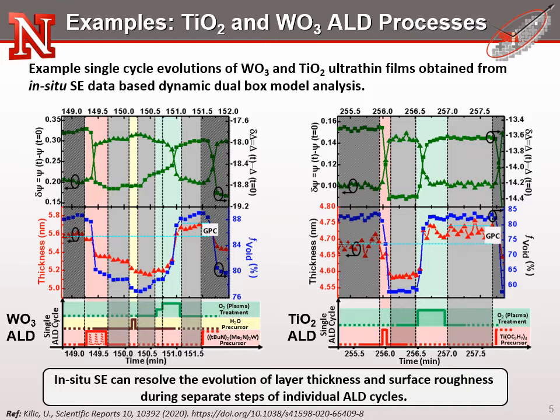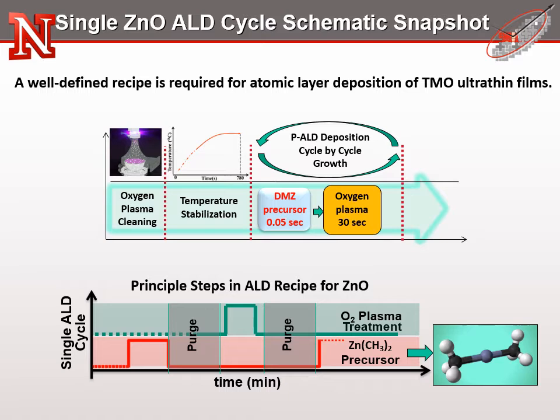As a consequence of cyclic exposure to precursor materials, we observe cyclic surface roughening with fast kinetics and subsequent roughness reduction with slow kinetics. This process leads to the oscillation of the thin-film thickness with small growth per cycle. Here, we would like to use this knowledge and study the in-cycle kinetics of the zinc oxide ALD process. However, first, the ALD technique requires a well-defined recipe in order to obtain continuous material growth with desired stoichiometry.